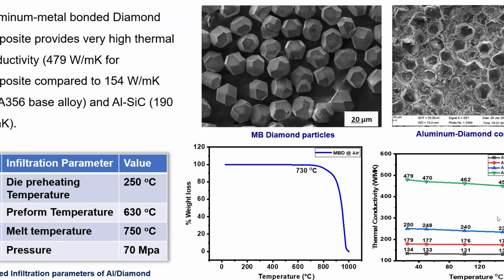When we evaluated the thermal conductivity of these compounds, we observed that the metal-bonded diamond particle shows 479 watts per meter Kelvin. Aluminum is 154 or 134 in as-cast conditions, increasing to 179 with synthetic diamond, 250 with natural diamond, and 479 when it is metal-bonded. So the structure of the diamond particles and their interaction with the aluminum lets you tailor the required thermal conductivity of all these materials.